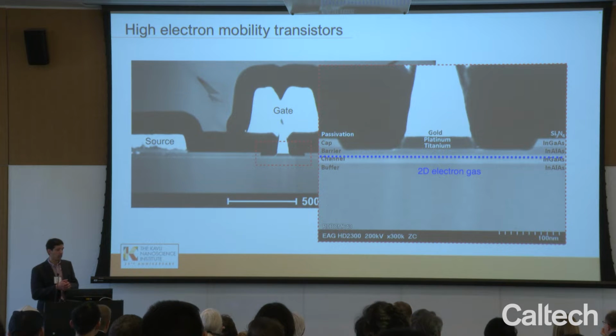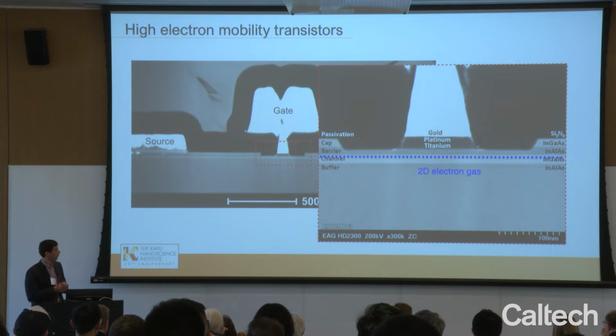And you can see how materials science and nanoscience over the past 30 to 40 years has allowed exquisite control of the materials and the thin films, with the atomic perfection at the interfaces that you need to create this two-dimensional electron gas with outstanding charge transport properties. That enables the high-frequency performance, which is how we communicate and do other things.